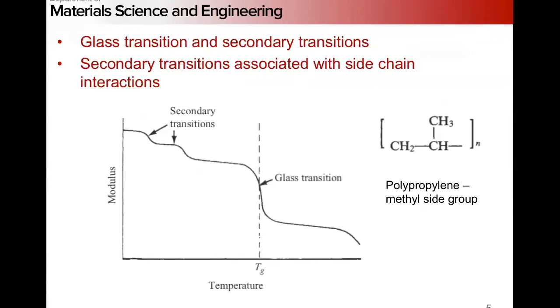So we looked at glass transition, right? If we look at the modulus as a function of temperature as we cool it down, we see a region where we get a sharp increase in the modulus, which we call the glass transition temperature. Then we have secondary transitions that happen at lower temperatures. We didn't talk about these secondary transitions before, but these are related mostly to side chain interactions, and we'll talk about them in just a little bit.